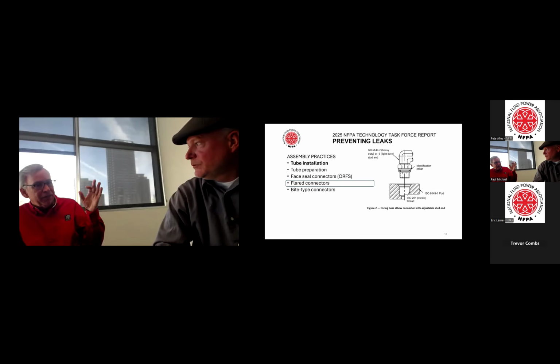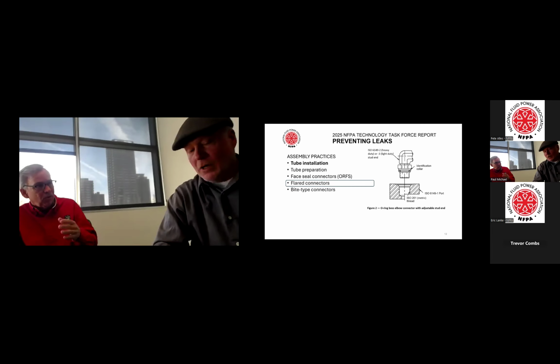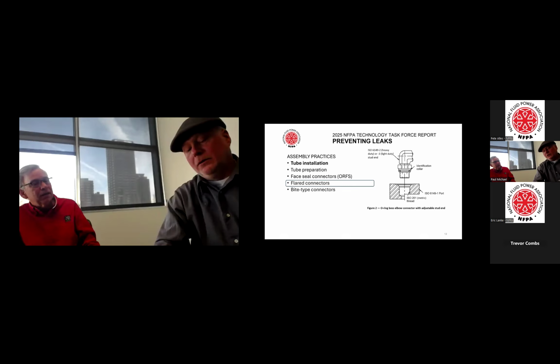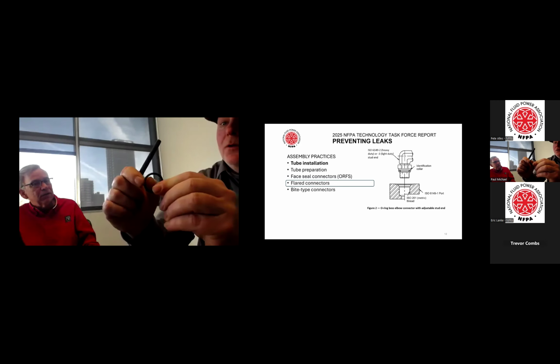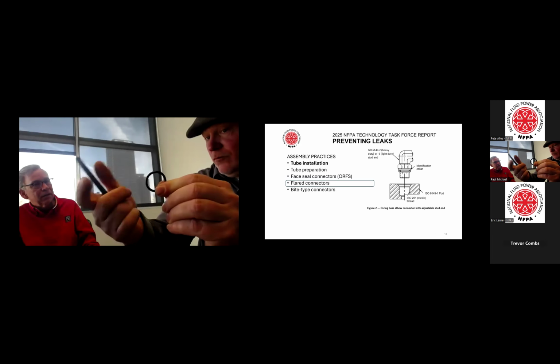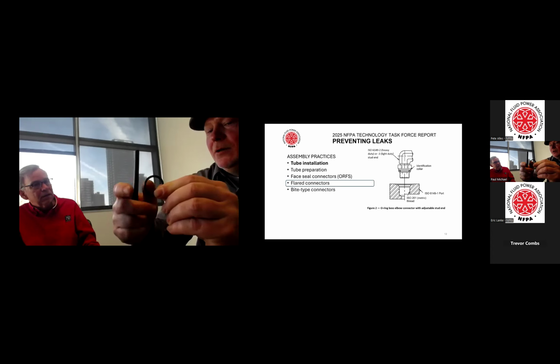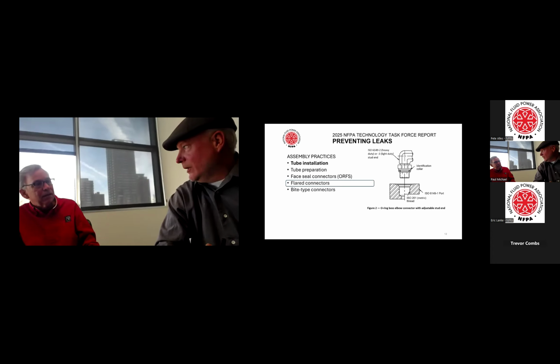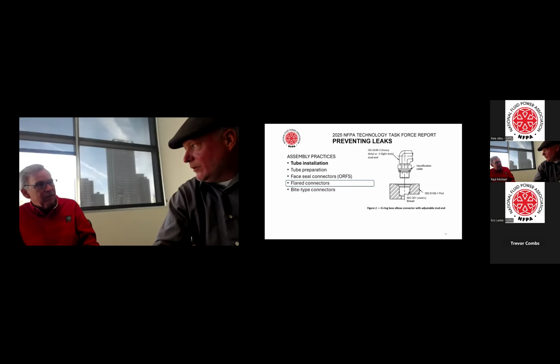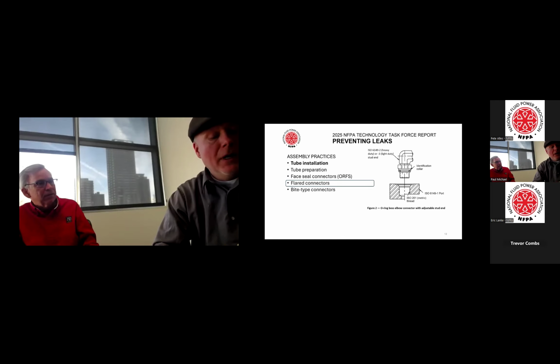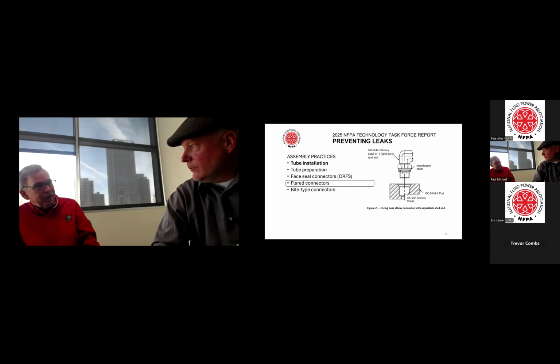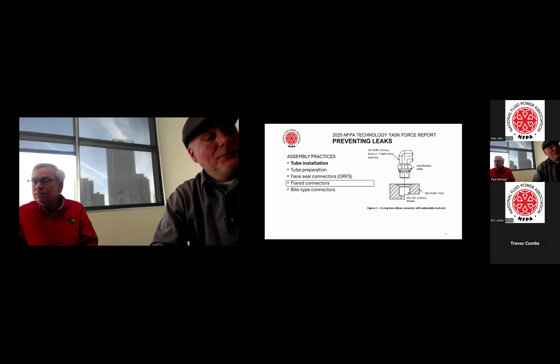Yes. Is it on the face as well as on the Boss? The O-rings are made so the cross section of the O-ring is here and here. It's because it's round, and the ID and OD are different. It's not a standard 1/8 inch 32nd cross section. Okay. So, and typically they're a 90 durometer. They're better for a static sealing application. The durometer is a little different, so they're a little bit harder and yes, better for static loading. Mm-hmm. Cool. Good insight.